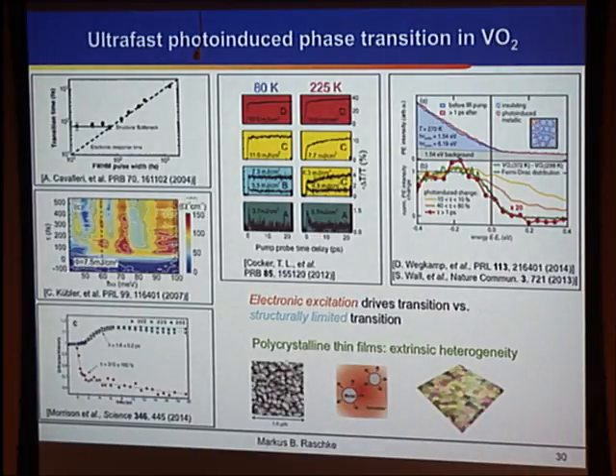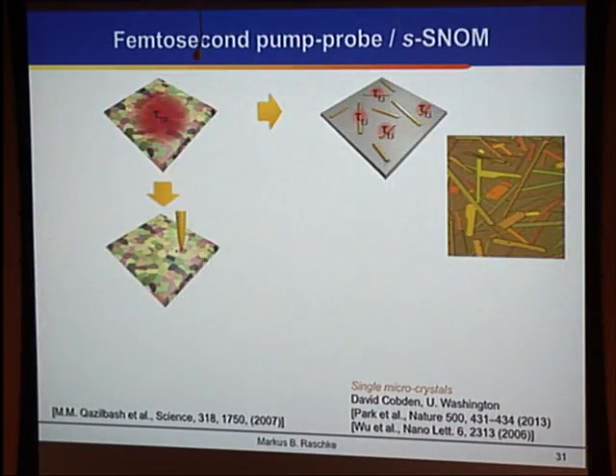Yet, as of today, it has been completely inconclusive whether it is an electronic excitation driven or a structural limited transition, largely because people have looked at extrinsically heterogeneous samples in the form of polycrystalline thin films. Also to avoid this problem, we started to look at single crystal structures, and then did a statistical analysis of pump probe measurements on single crystals, looking at different but well-defined crystals, to see whether there's a correlation with the nature of the insulating phase.